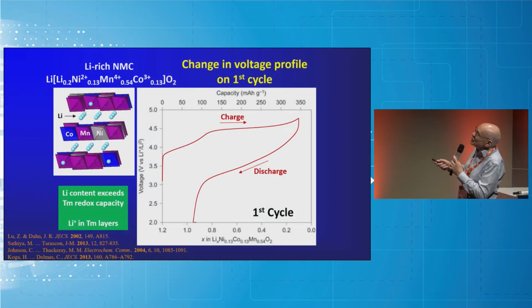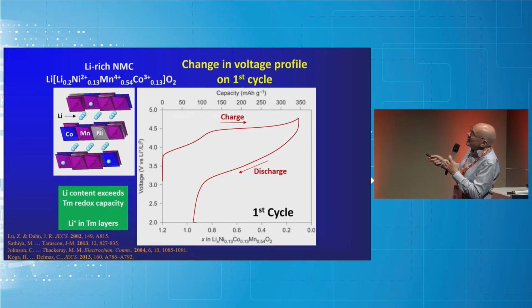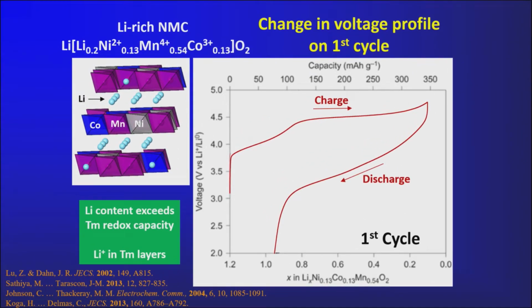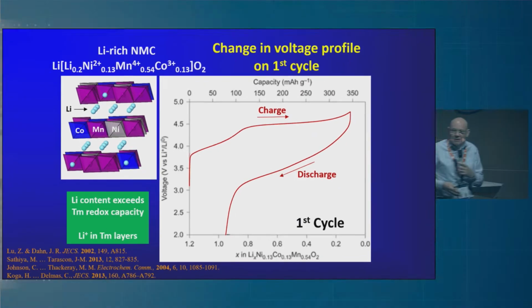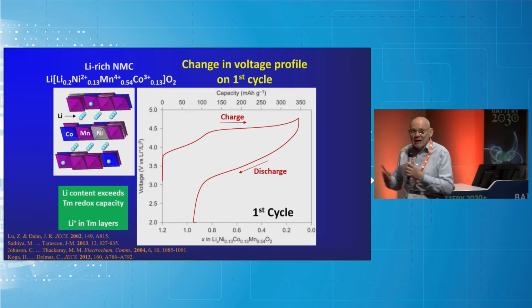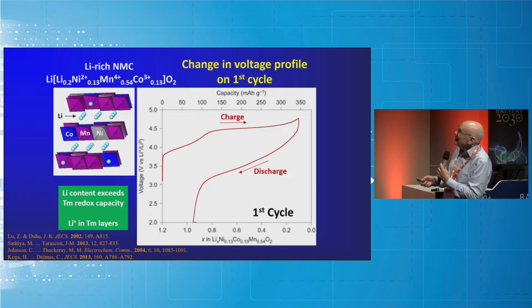But this is the archetypal lithium-rich layered NMC material. There's the composition up there. Classic layered crystal structure of our NMC-type cathodes. These are the transition metal layers. The light blue is the lithium. So these are the lithium ions in the transition metal layers. And of course, we have lithium ions in the alkali metal layers as usual. The point being that you have more lithium. You've got these extra lithiums compared with a stoichiometric NMC. So you have more lithium than the capacity to remove electrons by oxidizing the transition metals to their 4+ state. And so if you want to take that extra lithium out and get the extra capacity, you have to strip electrons from the oxide ions. And that's the whole point and the whole challenge of realizing these high capacity cathodes.